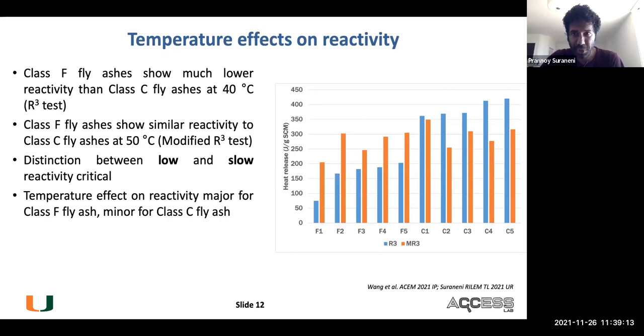Now, there is a temperature effect on reactivity. It's major for class F fly ash. From 40 to 50 degrees, you get a massive change in the reactivity. But it's not so important for the class C fly ash, where there is some effect of the temperature, but not so much. So if you're running a reactivity test at 40 degrees, it is very suitable for rapidly reacting materials.